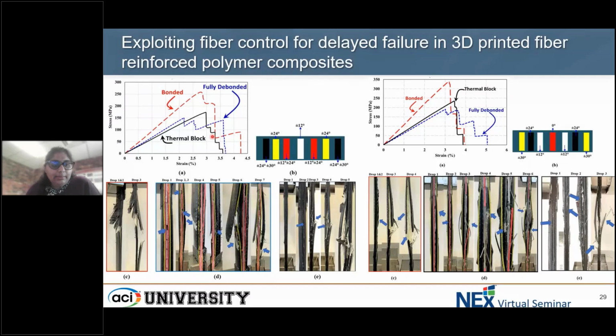If you see the black color line here, again a progressive stepwise sequential failure, thermal block, at a compromised load compared to the bonded, but definitely higher than the fully debonded because there is still some kind of bond to allow the shear transfer and therefore the strength increase, but there is not enough bond as the bonded to get that strength. However, the bonded had abrupt large drops, whereas the thermal block had smaller drops in load capacity.